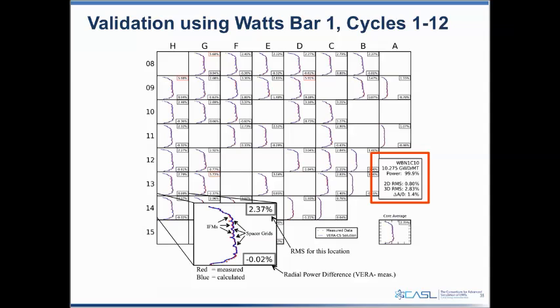In this plot, you see a quarter of the core. The blue and red, what look like lines, are actually comparisons of the computed solution in blue and the measured solution as red dots. For every single assembly where there's a flux detector, we're able to pull off the comparison of measurements and experiments, and in the bottom right corner of each box, the assembly average flux comparison, with the root mean square of the individual axially varying values in the top right corner.